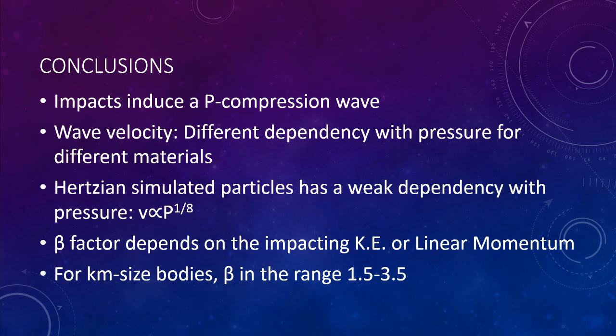That's something that we have to understand better, what is this big difference between artificial materials like gravel or glass beads. In the simulations, the Hertz and viscoelastic particle has a weak dependency with the pressure, with an exponent of the order of 1/8. And the beta factor depends on the impacting kinetic energy or the linear momentum. For these kilometer-sized bodies, we get a beta in the range of 1.5 to 3.5.